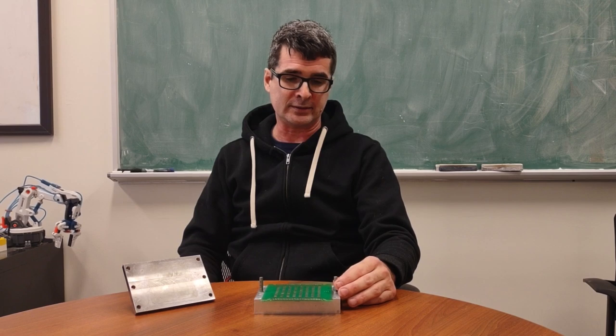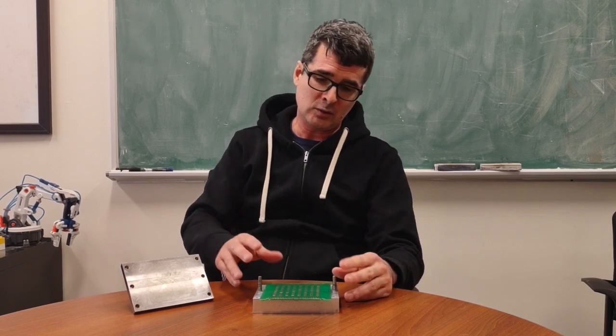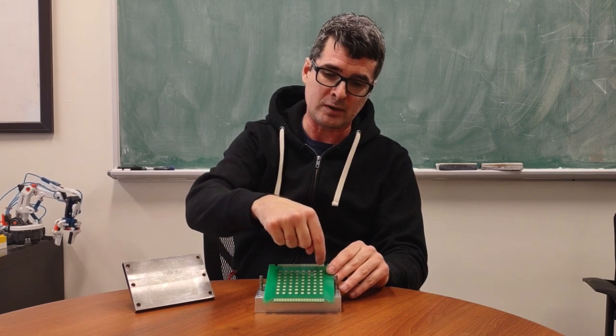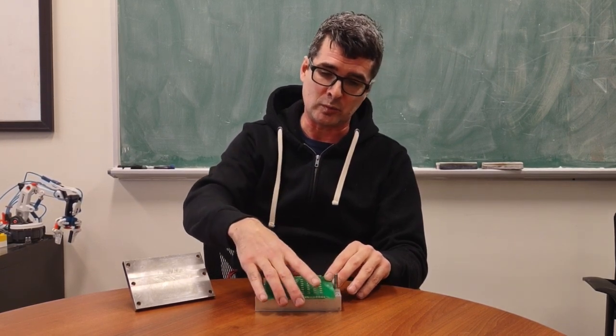But it doesn't give us a lot of information about long-term cycling because we run them for about 5 to 10 cycles. So we also developed for this project a high throughput measurement technique to determine how much transition metals are dissolved. So we did a week-long high temperature hold where the cell wasn't a single piece of lithium anymore. It was 64 different punched separators and lithium assembled into one cell.